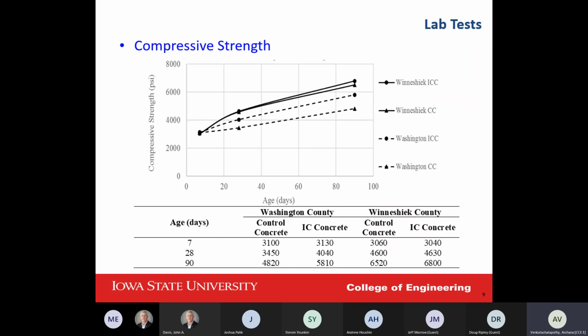So based on the lab tests in compressive strength, we see almost 10 to 20% improvement in both Washington and Winneshiek County. Our construction was in Washington County, which is close to Iowa City, and Winneshiek County, which is close to Decorah, if you're familiar with the Iowa area. In both of them, the solid line is Winneshiek County, and the dashed line is Washington County. And the circle is the one which has internal curing, and the triangle is normal concrete.